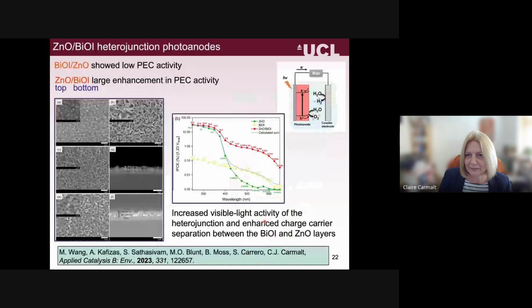So we looked at forming these heterojunctions, and we did it in two ways. One was where we had bismuth oxybromide as the lower layer and then zinc oxide on top. And then the other way around, we put bismuth oxybromide, sorry, it's not the bromide, it's the iodide, apologies. Bismuth oxyiodide on the bottom with zinc oxide, or zinc oxide with bismuth oxyiodide on top. And these are the SEMs. So this is the plain zinc oxide, and this is the bismuth oxyiodide. This is where you have zinc oxide on the bottom with your bismuth oxyiodide on top, and so it adopts a similar morphology to the bismuth oxyiodide.